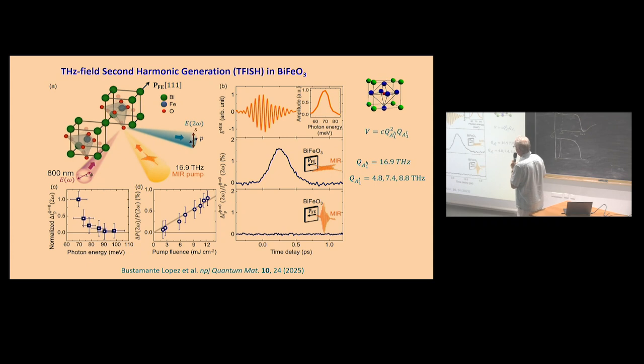Okay, slightly about bismuth ferrite. Bismuth ferrite is frequently mentioned here. This is also a very fresh paper. They excited a lattice mode at 17 terahertz and measured second harmonic generation. When the pumping was parallel to the probe, they were able to see a change of polarization. This is less than 2% change, but it exists. And when they pumped perpendicular to the polarization, there is no effect.